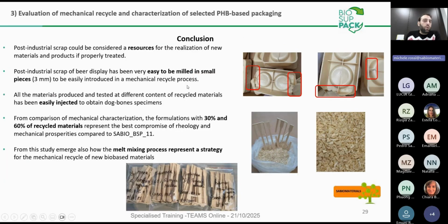So how can we conclude in this case? After the recovery of the post-industrial scrap and the milling, which is a typical process and is very easy to obtain, the material obtained has also been easily injected. For the results that we have obtained after the characterization, we can suggest that only 30% or 60% of the recycled material could be suggested to a potential waste management company regarding the reintroduction of scrap of bio-based material based on polyhydroxyalkanoate, in this case PHB, for a recycled material. We suggest to avoid the 90% and 100% of recycle due to the material properties that we have detected.